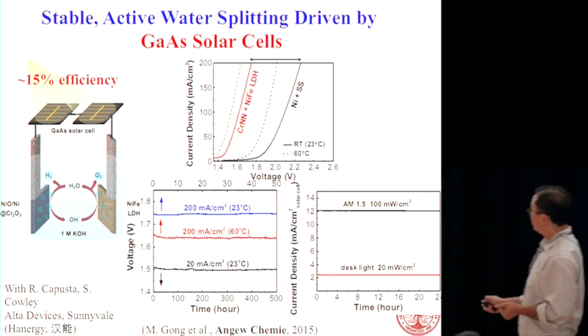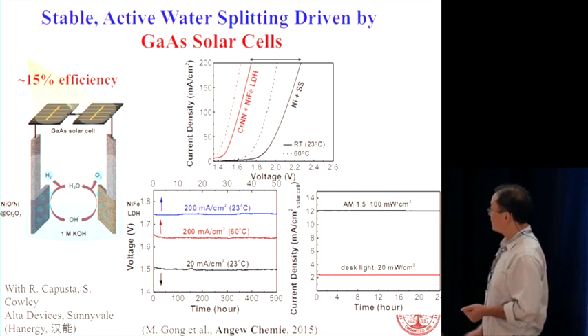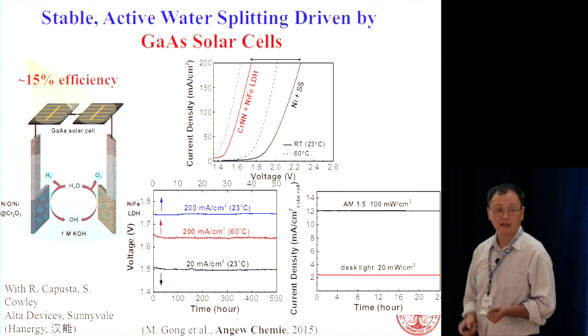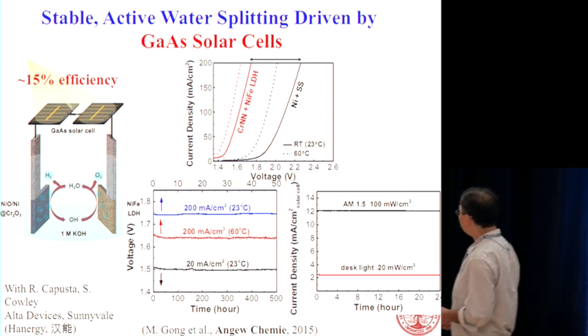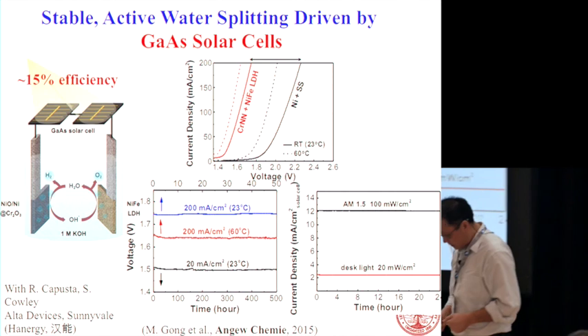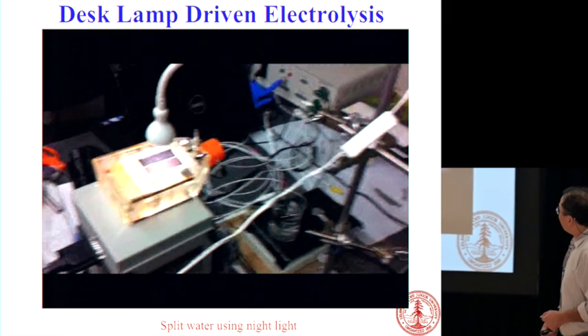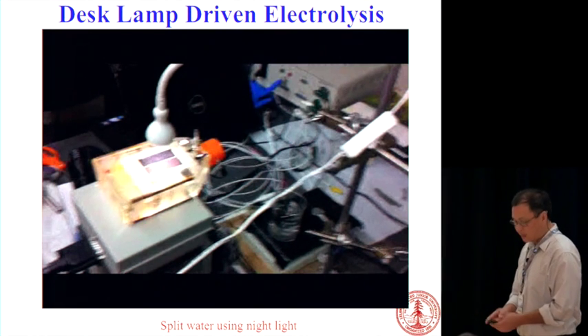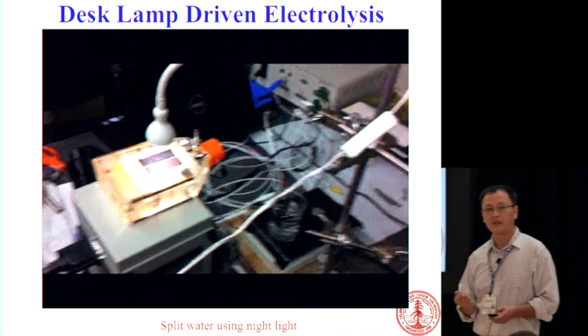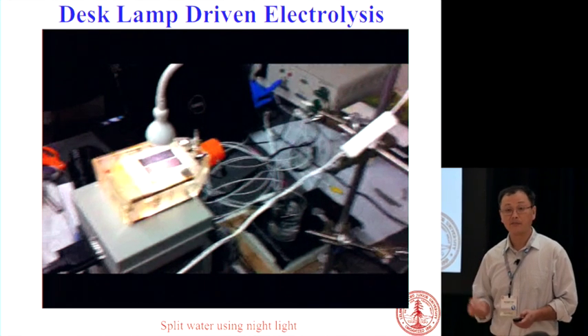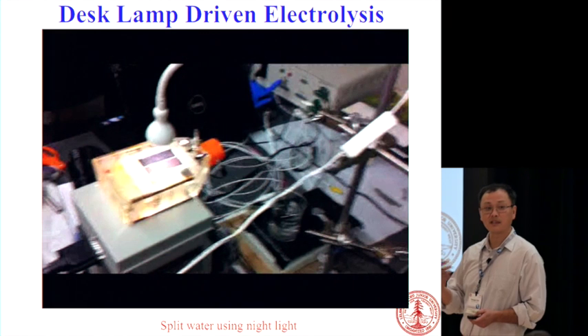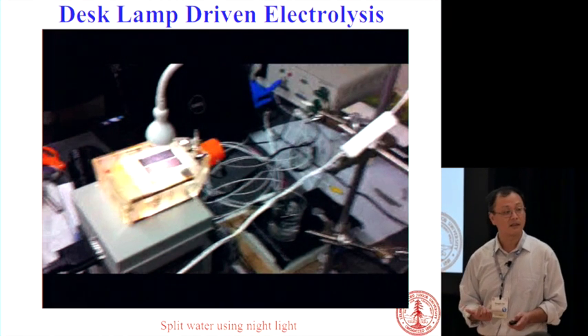What's also important is that it's quite stable. You can do this for 500 hours without much decay. So we figured out ways to stabilize these catalysts. We are also able to drive the water splitting using lamplight. You can do this at night. You don't need sunlight.